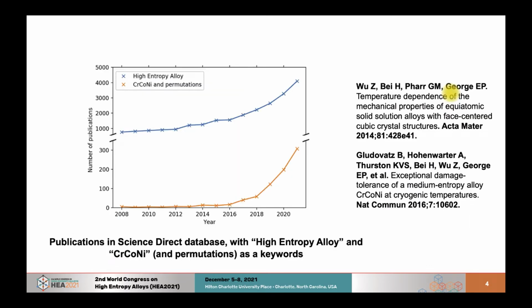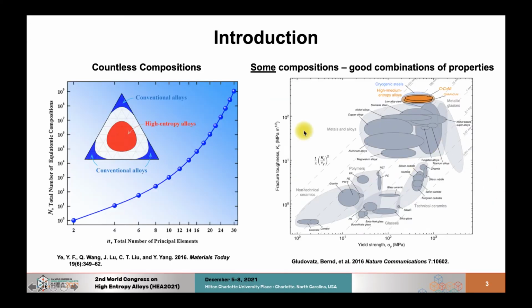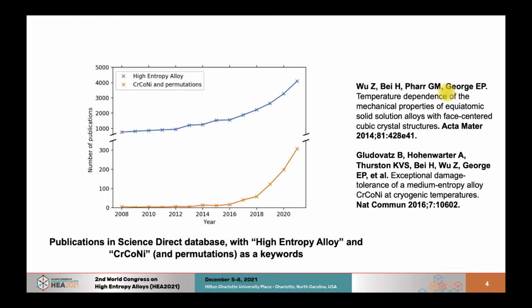So just to give a brief history outline on these alloy developments, by looking at the number of publications per year, we can identify that the study of chrome cobalt nickel alloys, which is the orange line here, really spiked after 2016. So in 2014, these compositions were produced by Wu. I'm going to mention this study later. And then in 2016, after this paper by Gludovatz, probably one of the most cited papers in the HEA literature, showed, among other things, this diagram that shows that chrome cobalt nickel are one of the toughest materials ever made among any material.